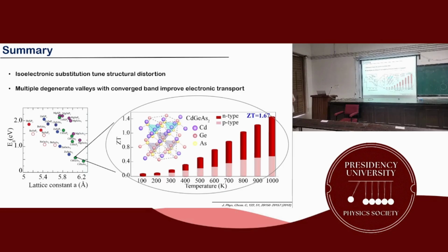That will not happen. And also, when the experimental group works synthetically, they will have different kinds of limitations, because we are working theoretically. There are various sources of scattering inside the body, and how the system interacts with your experimental setup and the environment can differ. So the theoretical value I am getting, we would say, is the maximum theoretically possible value. It's not exact; I cannot say that experimentally I will get this value. If you have a pure single crystal, you have some control on the scattering, and you can reach the possible maximum value, which is at least how we would say it.